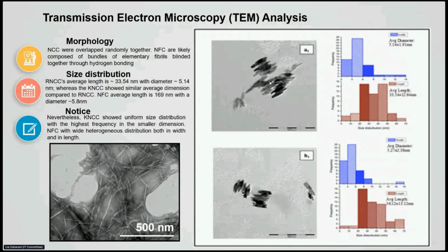Nanocrystalline cellulose and nanofibrillated cellulose both give a similar needle-shaped morphology, but nanocrystalline cellulose gives a much smaller size dimension. Both of them have a similar diameter: for nanocrystalline cellulose around 5.2 nanometers, for nanofibrillated cellulose 5.8, almost the same. But their length is different, a big difference. For nanocrystalline cellulose, the length is around 30 to 35 nanometers, but for nanofibrillated cellulose, it exceeds 100 nanometers. The average length is 169 nanometers in our study.